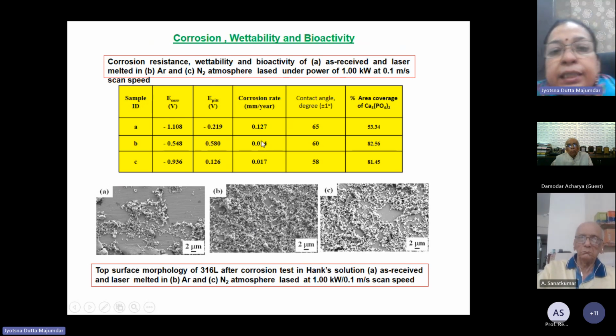In addition, the overall corrosion rate. If you see the contact angle, it doesn't change much, though it is lower than that of the as-received substrate. So the surface is more wettable, wettability increases. But more interestingly, if you see, bioactivity increases to a large extent as compared to that of as-received.